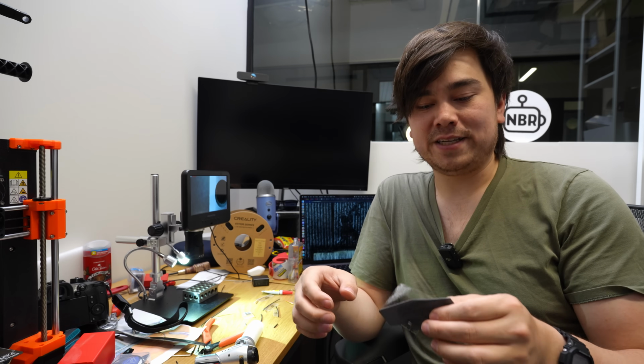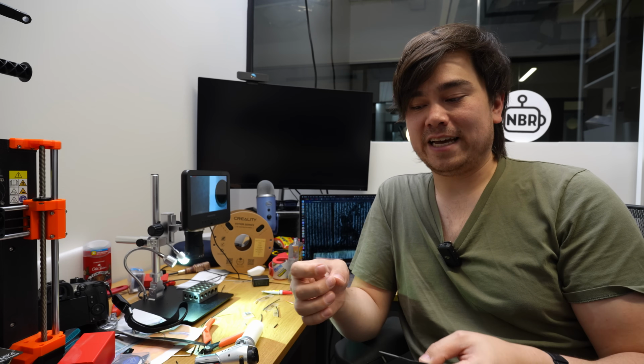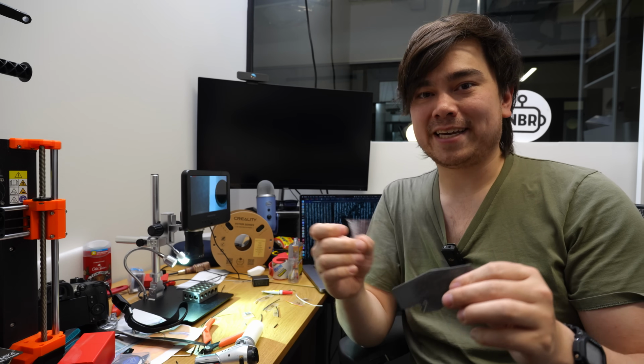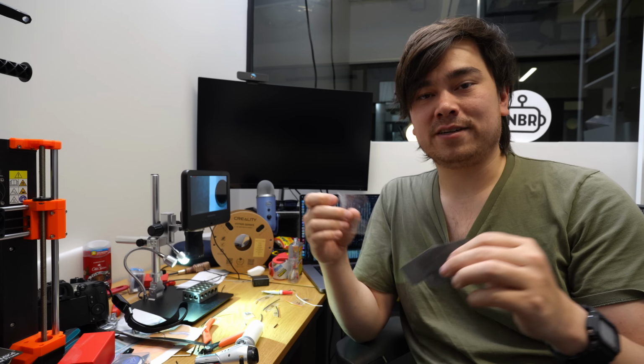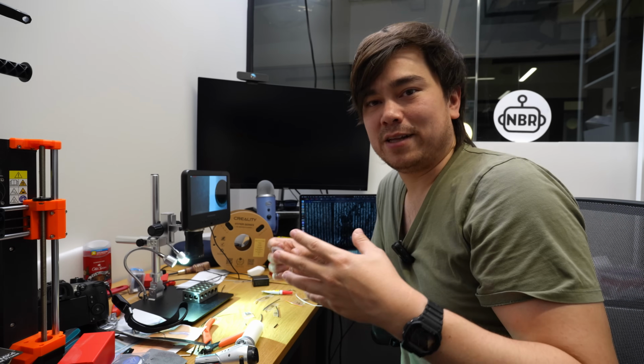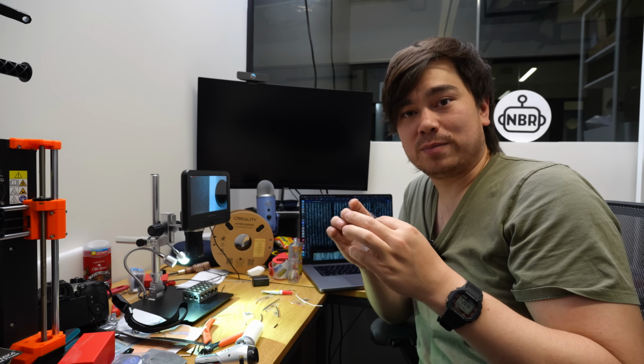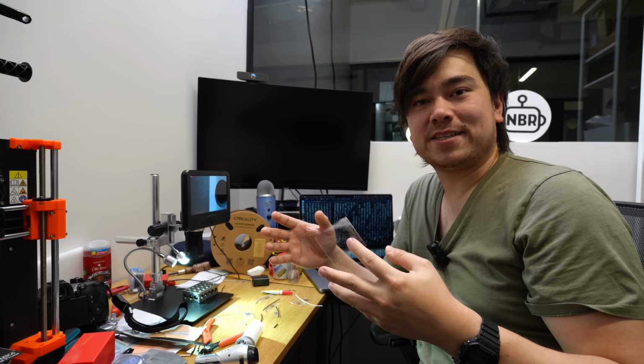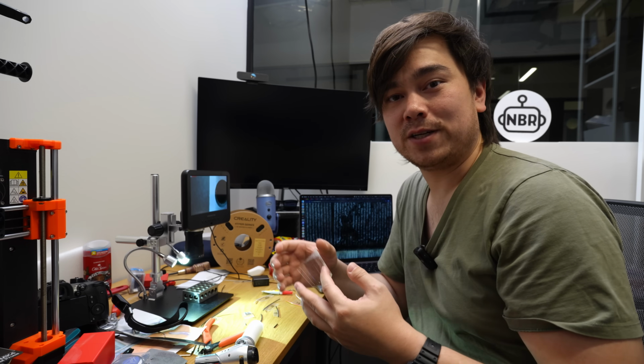This is HP's Multi Jet Fusion. This is a powder-based process that uses black ink to selectively heat and sinter the material. Basically, the black ink causes this white powder to absorb more energy, and that's how they can selectively melt the powder and create your 3D printed parts.